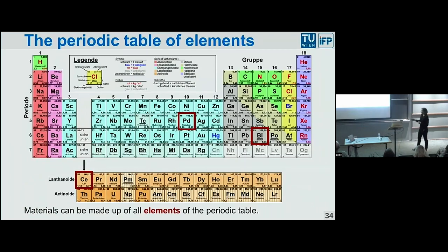And indeed, we put in a lanthanide, cerium, which has one 4f electron. Okay, all these here, you fill the very tiny f orbitals. But we put also other elements that are d elements that help to make this interaction, and a very heavy element that has very strong spin orbit coupling. So we put everything together that we think makes sense.